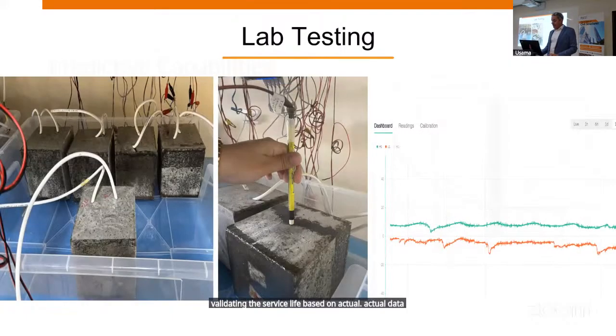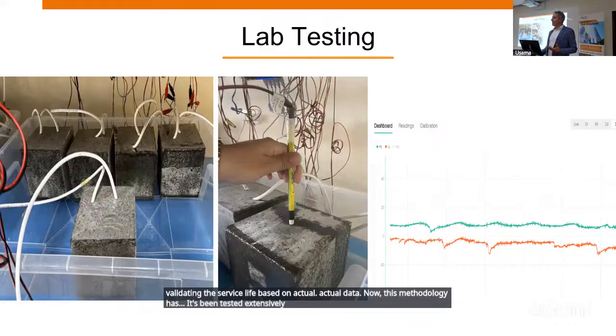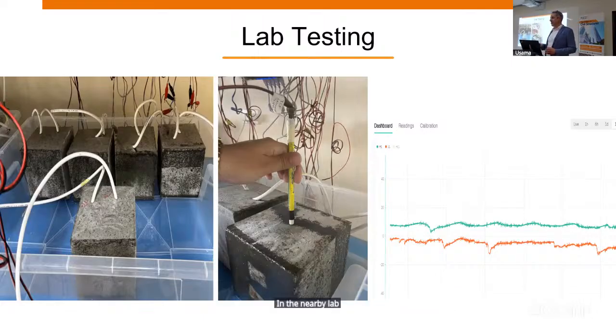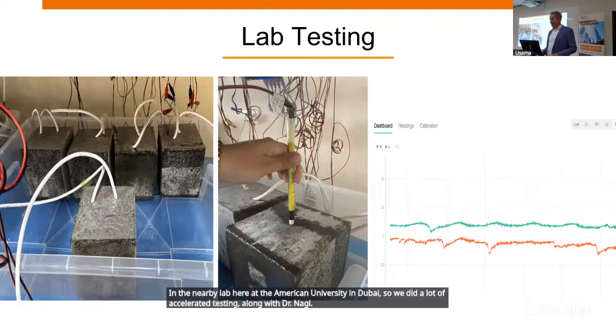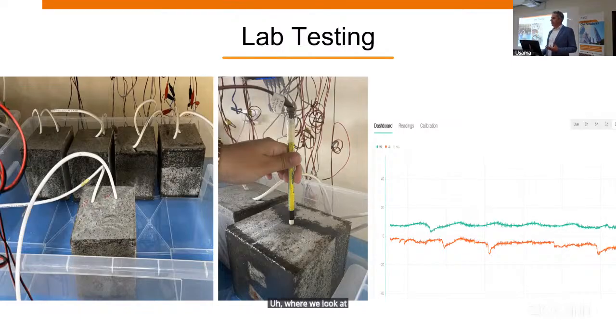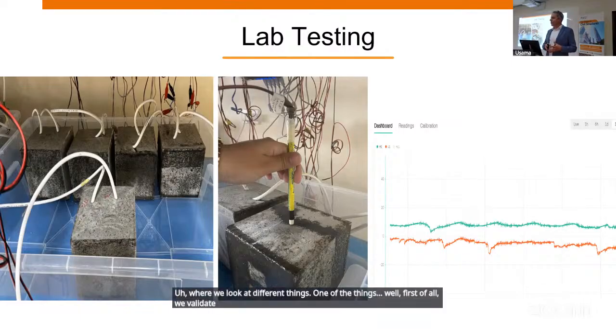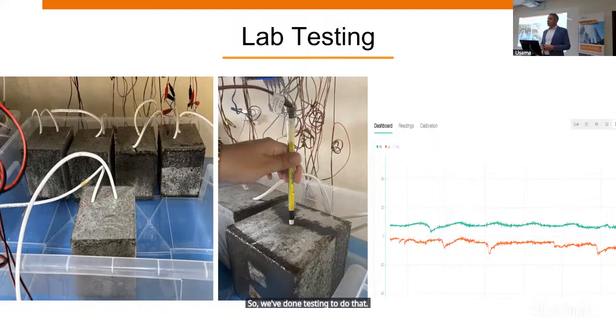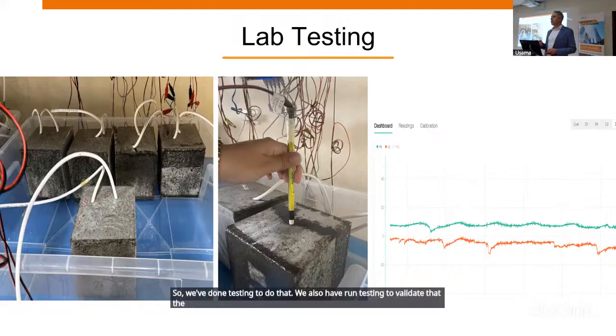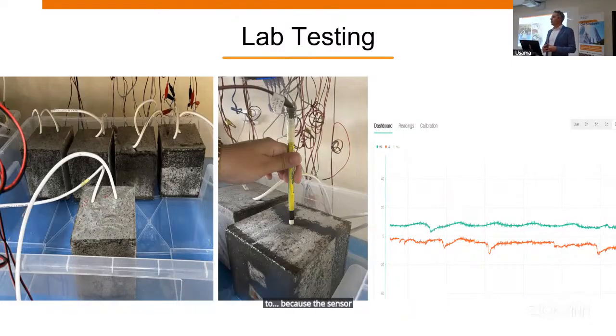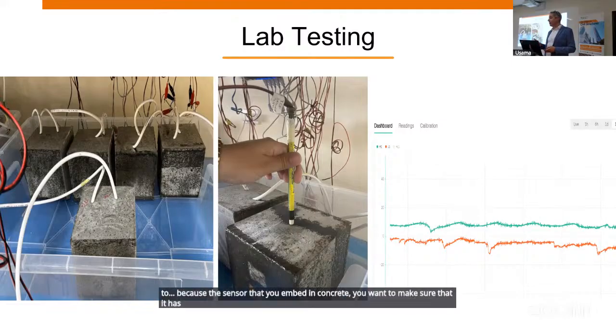Now, this methodology has been tested extensively in the lab through accelerated test methods. A lot of that was done in a nearby lab here at the American University in Dubai. So we did a lot of accelerated testing along with Dr. Nagy, where we look at different things. First of all, we validate that the data that we're getting reflects reality. So we've done testing to do that. We also have run testing to validate that the sensor will continue to give us the data throughout the service life. Because a sensor that you embed in concrete, you want to make sure that it has the functional life of the concrete.